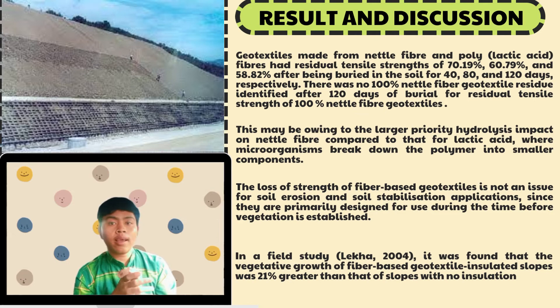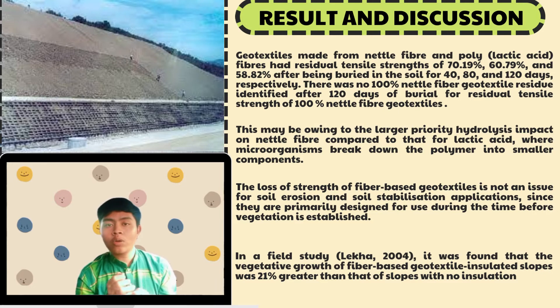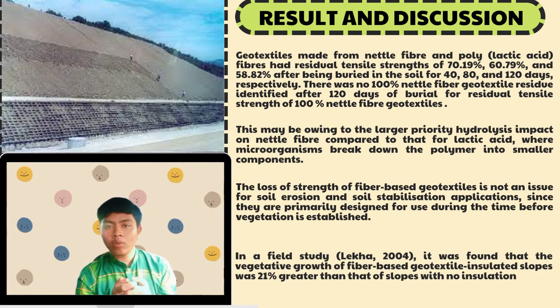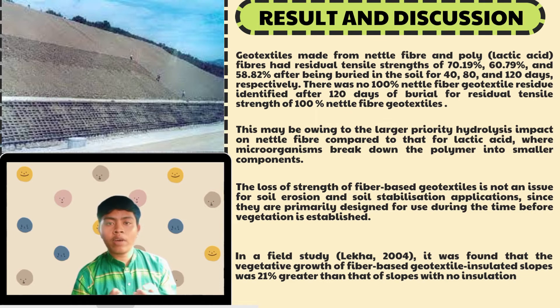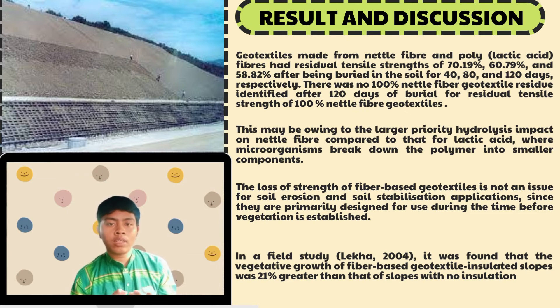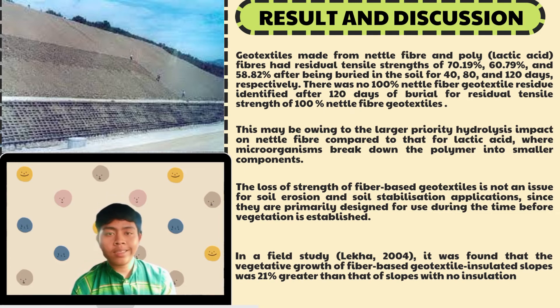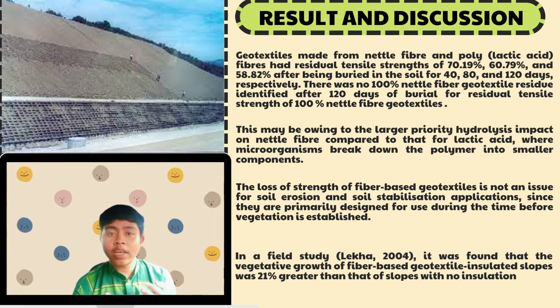After being buried in the ground for 40, 80, and 120 days, geotextile made from 100% polylactic acid respectively showed residual tensile strength of 70.19%, 60.79%, and 58.82%. After 120 days of burial, there was no trace of 100% nettle fiber geotextile, indicating that they had lost all of their tensile strength. This may be due to the nettle fiber undergoing a higher rate of hydrolysis than polylactic acid, in which case microorganisms are responsible for breaking the polymer down into smaller components. Since fiber-based geotextiles are mainly intended for use during the period before vegetation is formed, the weakening of their strength is not a concern for applications including prevention of soil erosion and destabilization.